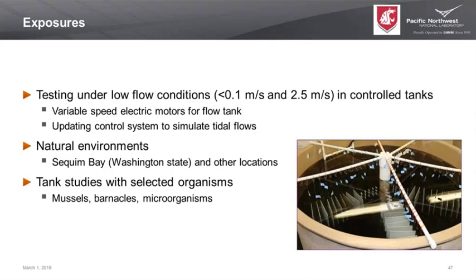But in wave energy and tidal energy settings, we're typically looking at velocities that may be as low as 2.5 meters per second, sometimes even lower. Off the coast of Orkney Island, they're fortunate in that they have some of the highest tidal velocities that there are, but here in the United States, for example, off of Oregon and in the Straits of Juan de Fuca, 5 knots, 2.5 meters per second is about our peak velocity.